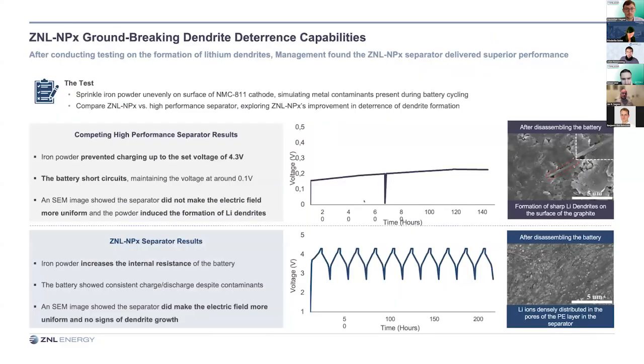We also did an exciting internal test where we took iron powder on a NMC 811 cell on the cathode to simulate what happens during contamination. The conventional separator battery cell couldn't even take a charge. It just short-circuited at once. With our separator, it just kept going, no worries, and it went completely fine.